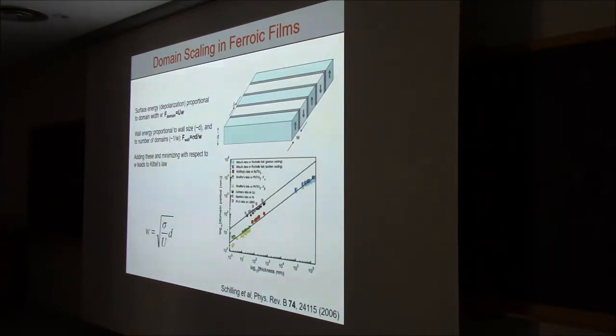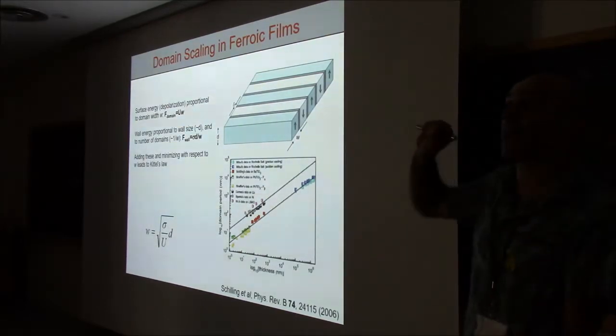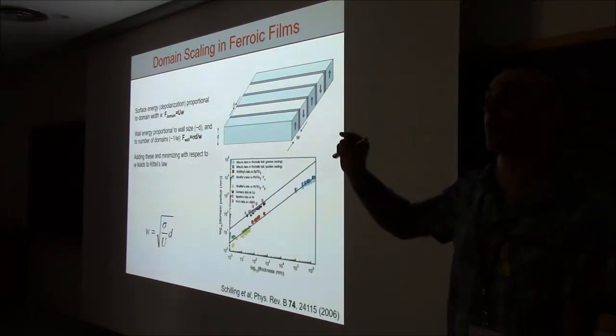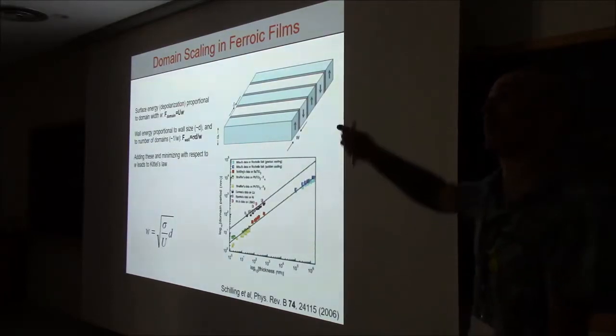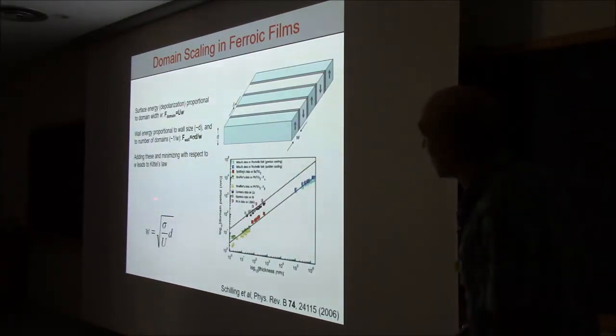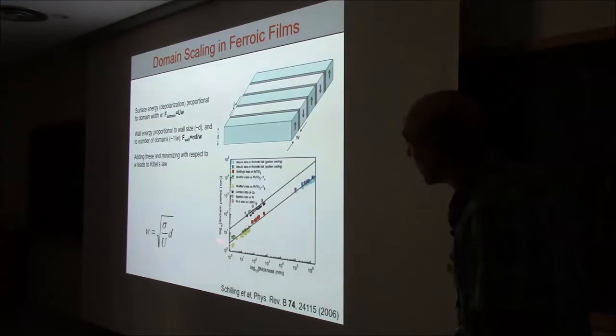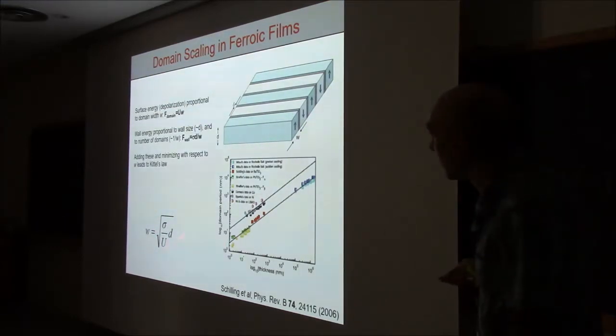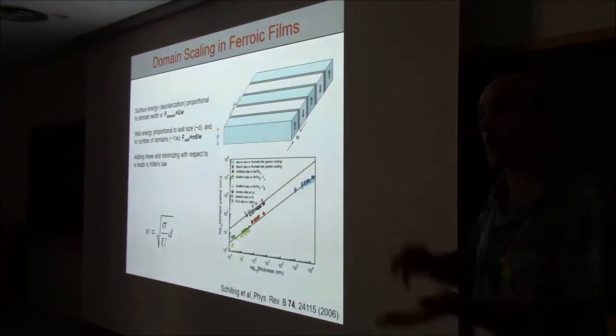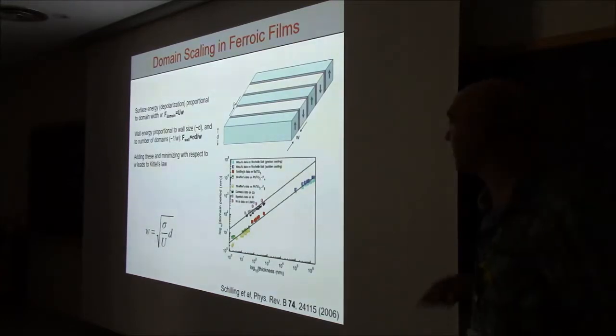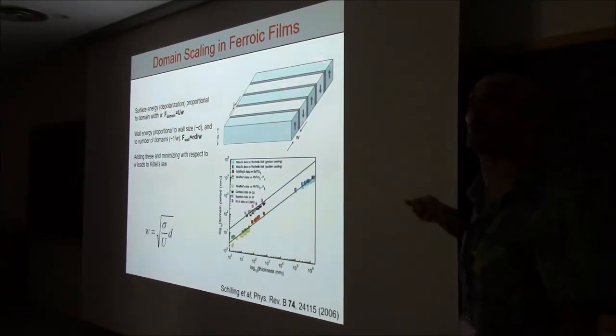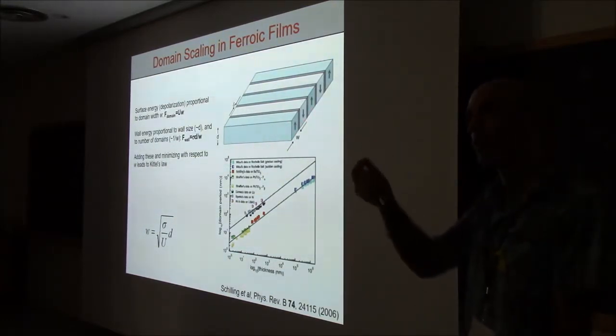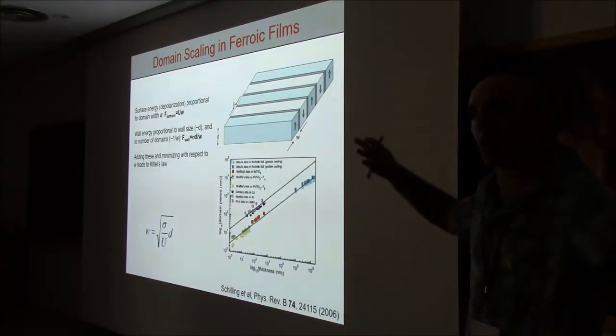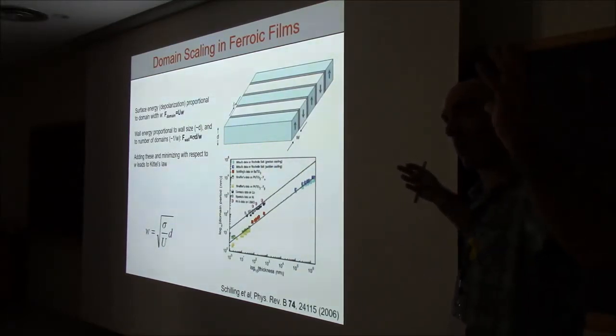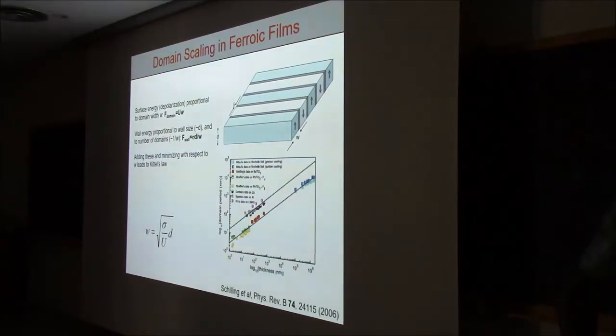Importantly also, as you make your film thinner, the energy cost of creating a domain wall becomes smaller, so you can have more and more domain walls. Basically, this is to say that domain size scales with film thickness. So the thinner your film, the smaller your domains, and you'll have more and more domain walls. So the properties of domain walls may affect the overall behavior of your sample. Okay.